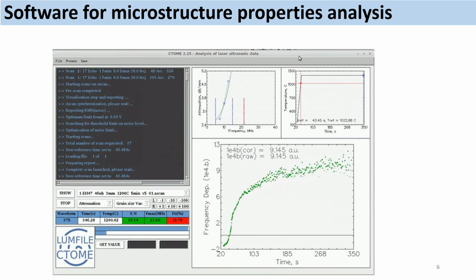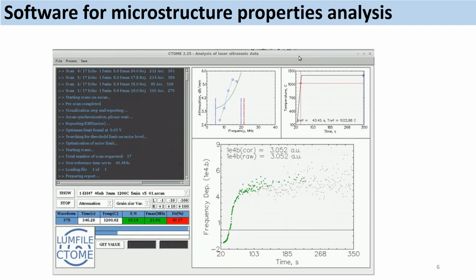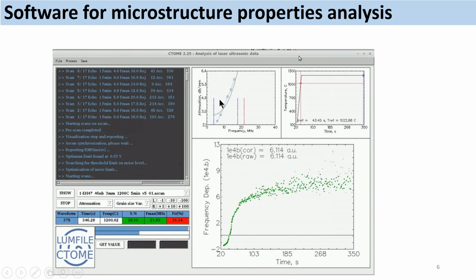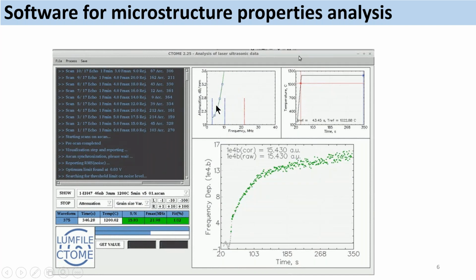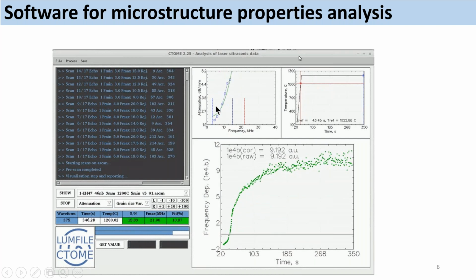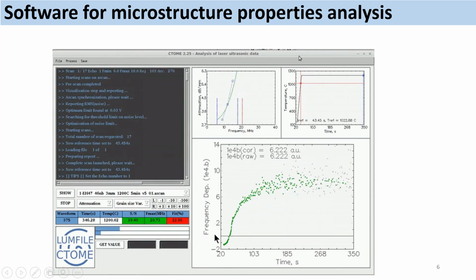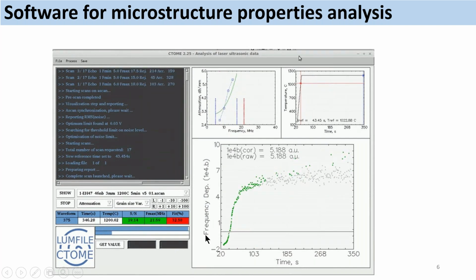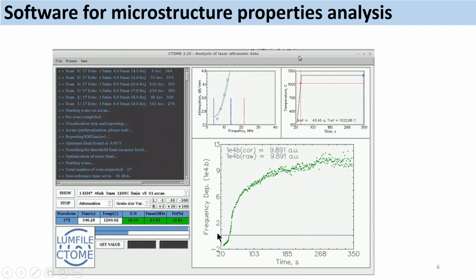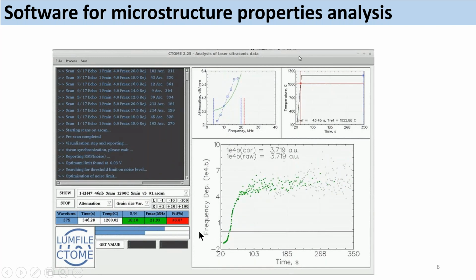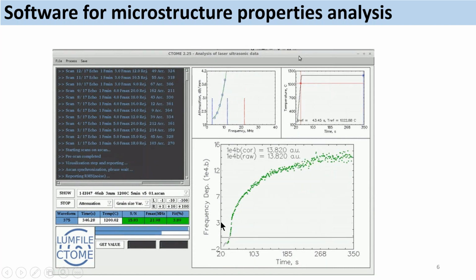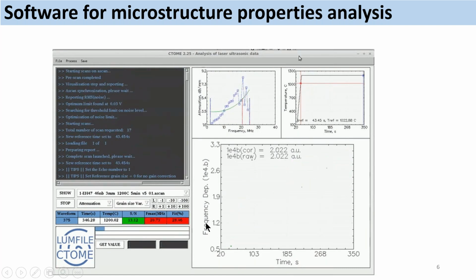To ease the analysis of those ultrasound signals for metallurgists, we've developed a software dedicated to the analysis of the properties of those ultrasound signals, in order to provide the metallurgist directly with microstructure properties such as grain size, or fraction recrystallized, or fraction transformed during a phase transformation, as you will see.